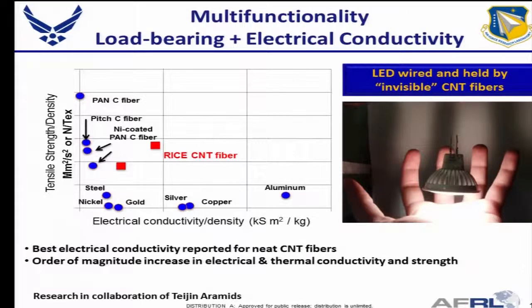The red dots here represent the carbon nanotube fiber that was synthesized at Rice University. And you can see, if you compare that to the metals, typical metals here, the conductivity of it is pretty good. It's approaching that of silver. However, the strength is much higher. And so you can look at that as a strong conductor, I mean a strong, mechanically strong conducting fiber.